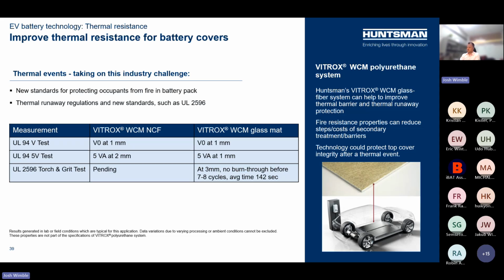And at 3 millimeters, this can meet some pretty aggressive cycles of UL2596. I think most folks are probably familiar with it, but it's the direct torch at 1200 degrees Celsius, blasted with superheated metallic debris in various cycles. And the results that we're seeing in the pending testing from non-crimp fabric also show outstanding performance. Some of our customers, through their simulated UL2596 tests, have seen even more cycles passed at 3 millimeters than we have in our 2596.